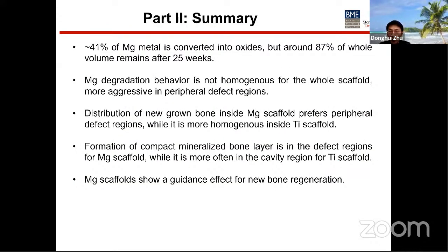Here's a summary for the magnesium bone alloys. About 41% of metal is converted into oxide, and around 87% of the whole volume remains even after 25 weeks. However, the ratio between degradation product and metal changes with oxides increasing over time. Magnesium degradation behavior is not homogeneous for the whole scaffold, being more aggressive in the peripheral region.